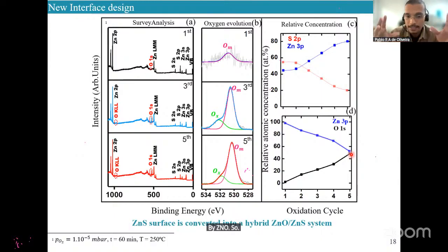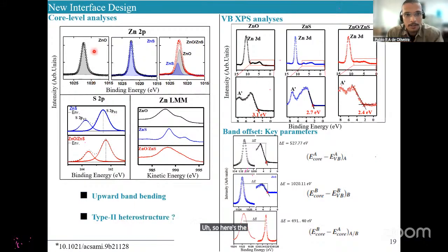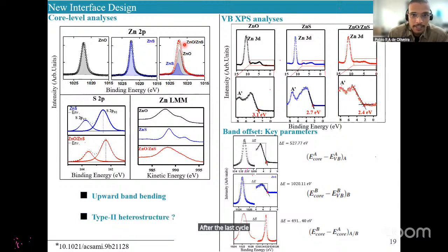So basically, by carrying out this experiment under these conditions, ZnS is converted into a hybrid ZnO-ZnS system. So you can try to figure out what happened from an electronic point of view by computing the core-level analysis. Here's the ZnO sample. It's a reference sample, ZnO 0001. This is the former ZnS, let's say the doped ZnS system, but before the reactivity. And this is the ZnO-ZnS interface after the last cycle. We can now resolve this peak into 2 components. Now we have the ZnS feature and the ZnO feature.